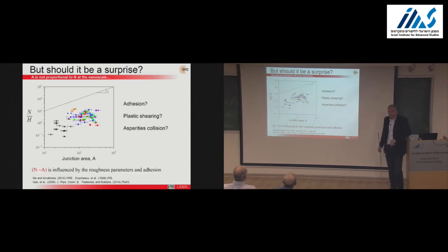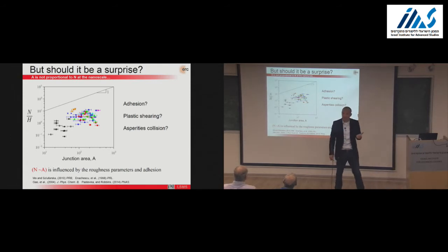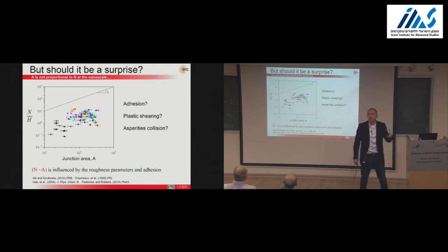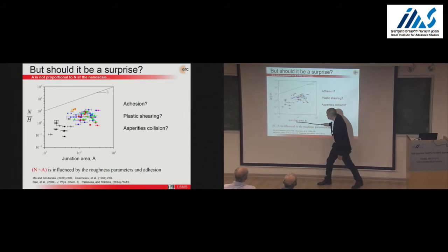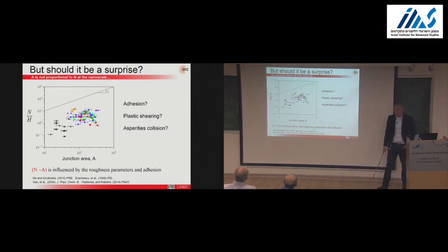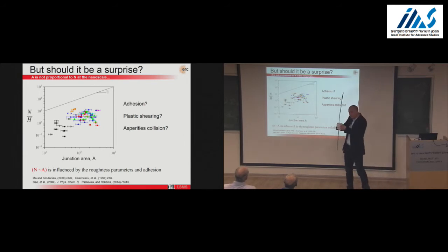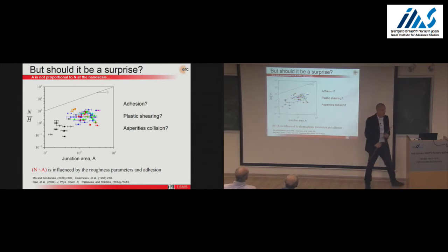It should not be, in fact, totally a surprise, because in the Archard model, we assume there's a proportionality between a normal force and a real contact area, but we lose this here at the nanoscale because we have adhesive forces. So the fact that we have adhesion makes us lose this proportionality between contact area and N over H. We have also plastic shearing. So our contact duration is not the junction size, but there's going to be a plastic flow, a kind of a necking of a junction that you form.